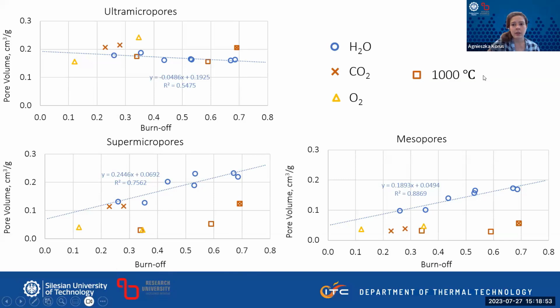Interestingly, at 1000 degrees, even the measurements that were using steam, for example, these two that you can see here, they didn't really follow the trend. Also, using only CO2 or using oxygen didn't manage to develop super micropores and mesopores. The ultra microporosity was behaving pretty much the same for all the samples, so it was just slightly decreasing with time.